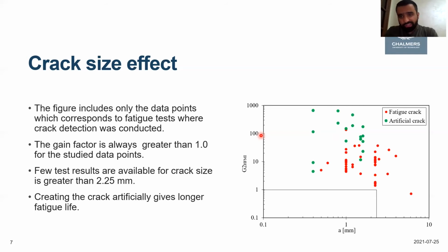Also, another side observation is that when the crack is created artificially, the gain factor is much higher. This is, of course, understandable, because this kind of artificial crack, created by machining, lacks a plastic zone area, which gives very conservative results. So this is not the best way of presenting a fatigue crack. An authentic fatigue crack can be created by fatigue testing.